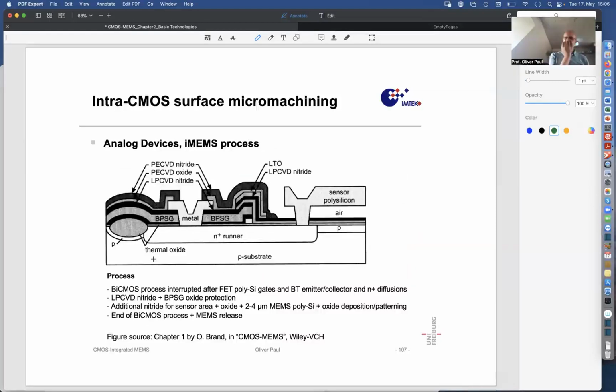Okay. Here is another variant also by Analog Devices. They call it the IMEMS process, and so they again have some CMOS part. The BiCMOS process is interrupted after the field effect transistor polysilicon gate fabrication, and the bipolar transistor emitter, collector, and n plus diffusions. So some of the structures are done, and then there's an LPCVD nitride covering everything for protection. On top of that, this MEMS poly is grown. And then finally, the remaining process steps of the CMOS and bipolar process are done. And then this can be under etched again. That's the MEMS release.